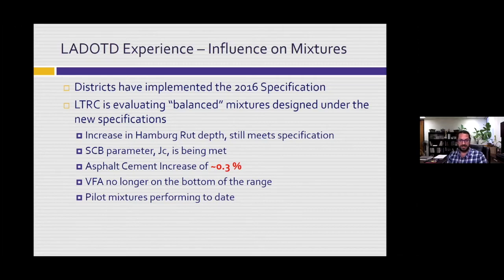And the asphalt content has increased. It was ranging from about 0.2 to 0.4. It's now settled down to around a 0.3% increase in asphalt content. The VFA is no longer at the bottom of the range. Again, the range used to be 68, and pretty much most of our JMFs were around that 68 to 70 range. Now, with the new limit of 72, they're sitting around the 74 range. So they're no longer just sitting at the bottom of our specified range. And the pilot mixtures are performing to date.